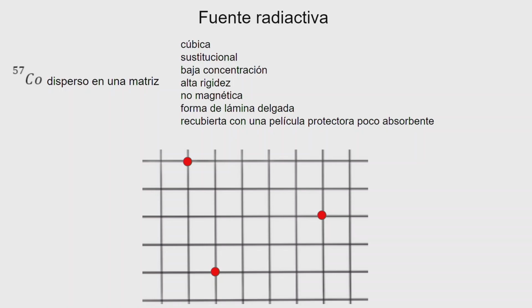But of course, your probes must be sufficiently separated from each other so that there are no interactions between the cobalt-57 impurities. Otherwise, they will produce some sort of hyperfine interaction that will be present in your spectra. Okay? Of course, the diffusion of the cobalt-57 into the rhodium matrix must be made very carefully, so that if there are some interactions, they are very minor and statistically will not affect your spectra.